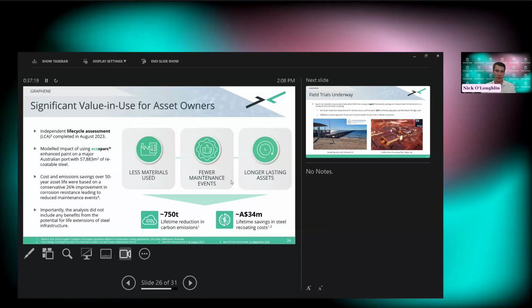So this is a life cycle assessment that we conducted last year. We looked at a variety of different steel infrastructure. This particular piece of infrastructure was a large jetty, a large port, and it had about 58,000 square meters of recoatable steel. And we showed that over the lifetime of that asset, you could save about 34 million Australian dollars just by using a graphene enhanced paint with EcoSparc. So quite significant for literally no change in what the asset owner would be doing. And we're generating those savings through basically fewer maintenance events. So instead of having to recoat the infrastructure every 6 years, you can push that out to 8 or 9 years. That's the premise on which this study was done.